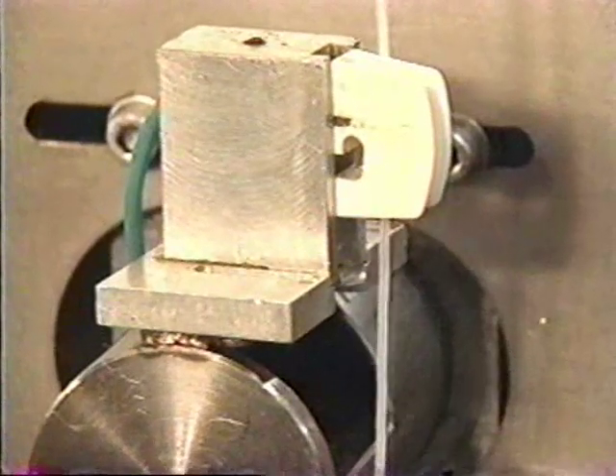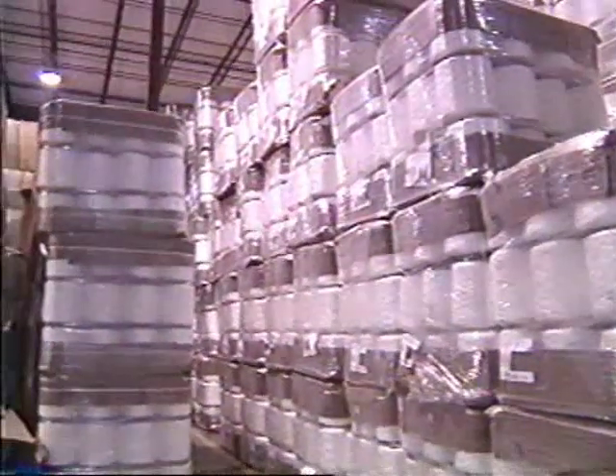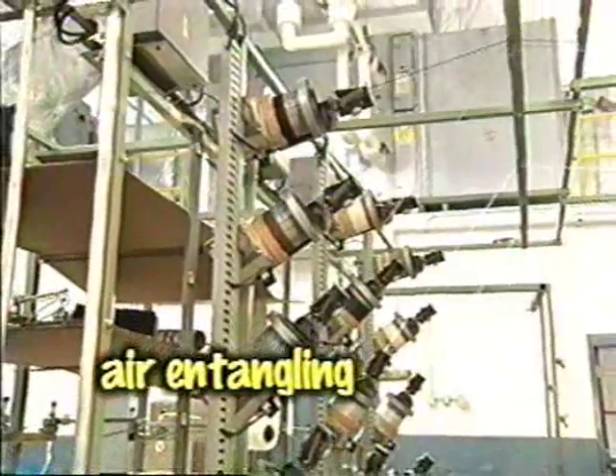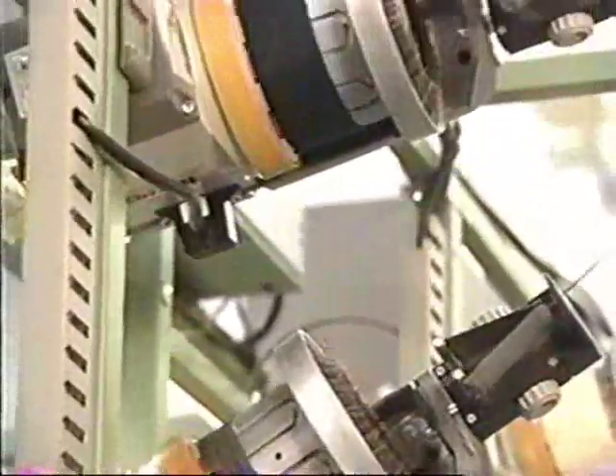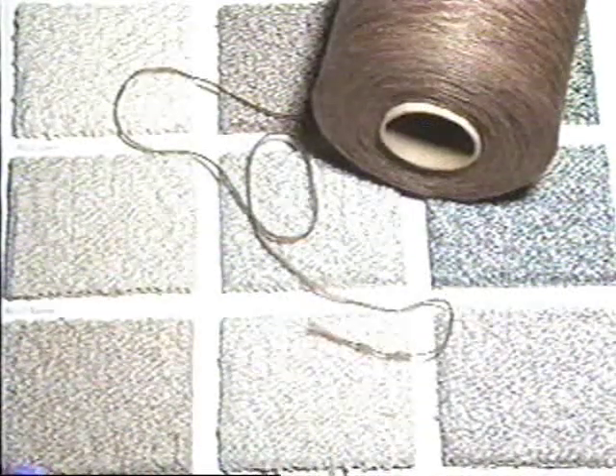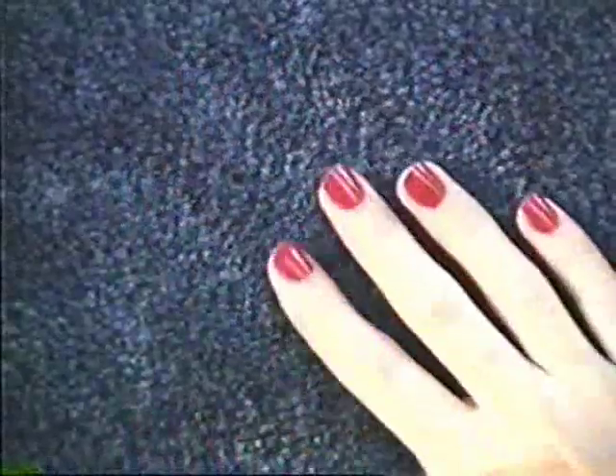Yarns made with continuous strands of fiber, or BCF, get to skip several of the steps used in manufacturing staple yarn. Because filament fiber arrives at the yarn plant already on cones, it only needs to be twisted and heat-set. Some BCF yarns go through a process called air entangling, which combines multiple ends of the filament. As the filaments are passed through an air jet box, high-pressure air mingles the filaments into one bundle. This process, typically used in making loop pile or berber construction, increases color flexibility and provides a way to make larger bundles of yarn by entangling two or more plies. Because every BCF fiber runs the continuous length of the cone of yarn, each fiber in the bundle cut by the carpet tufting process will be the same length, meaning little, if any, pilling will be left on the finished carpet.